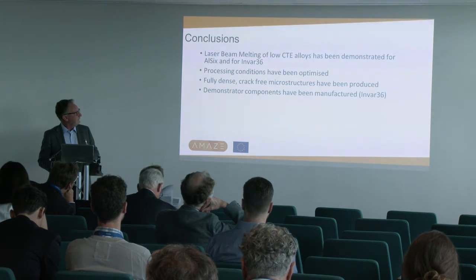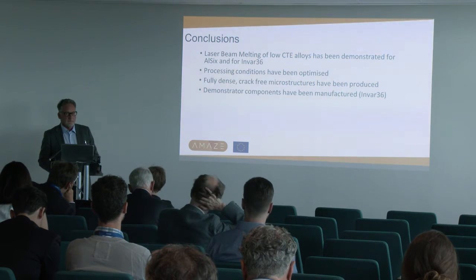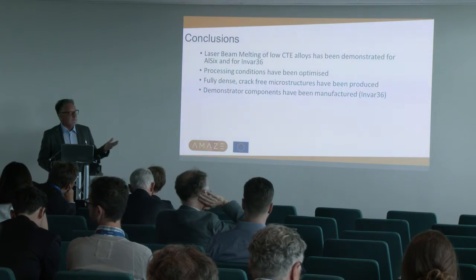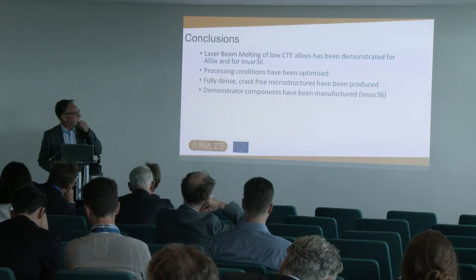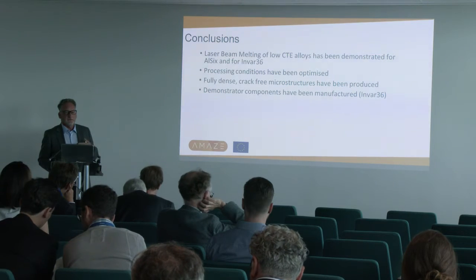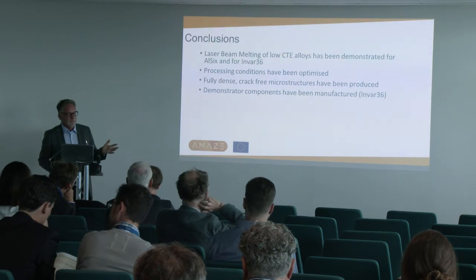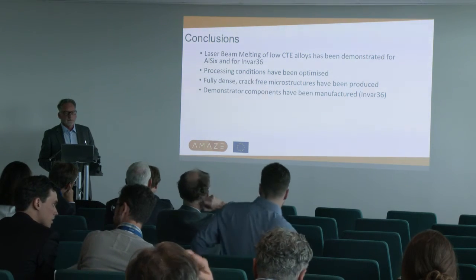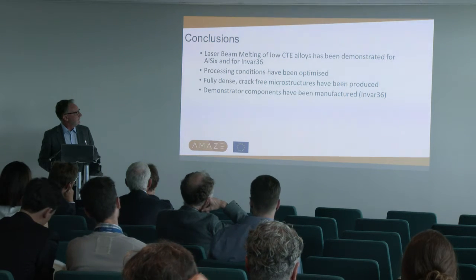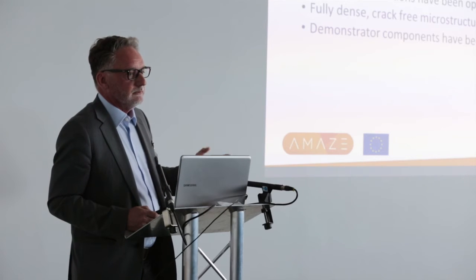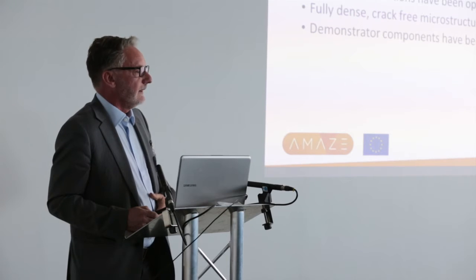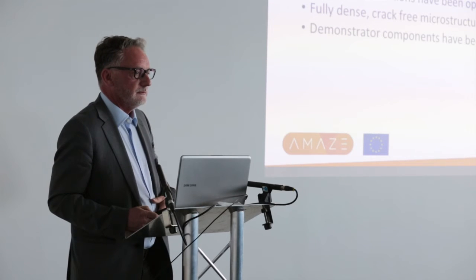So the conclusion is that we can use laser beam melting for these low CTE materials, and we've demonstrated it both for aluminium silicon and for the INVAR. The processing conditions can be optimized in the normal way as you do for laser beam melting, by adjusting the speed and power. And we can produce fully dense, crack-free microstructures in these materials, allowing, in the end, some demonstrated parts to be made.